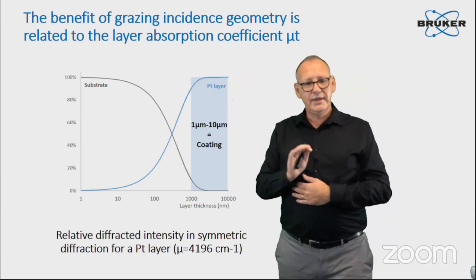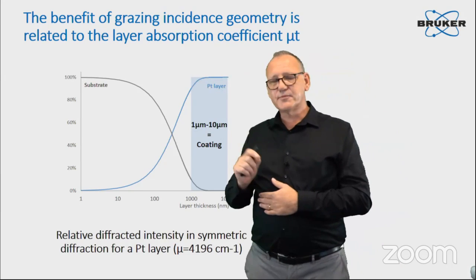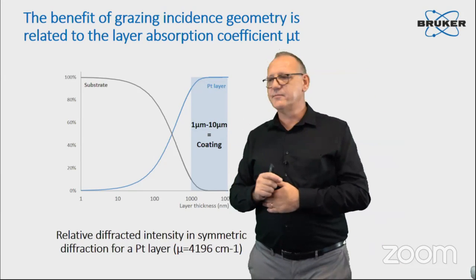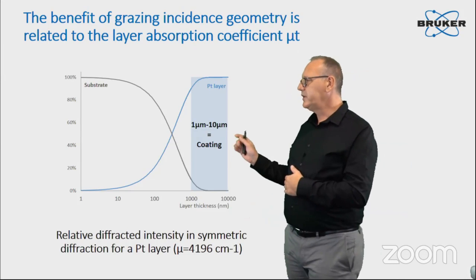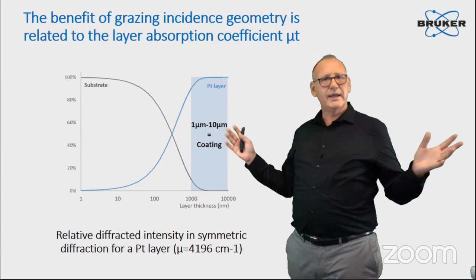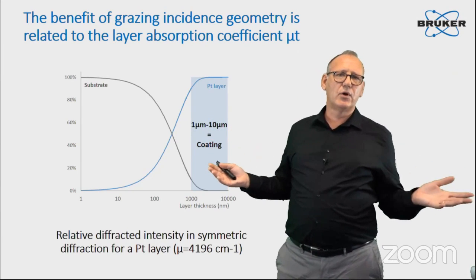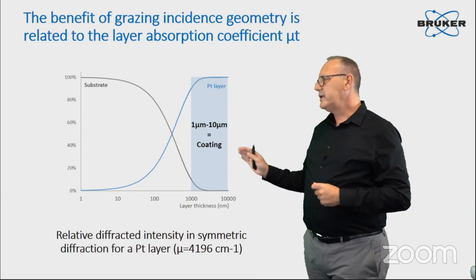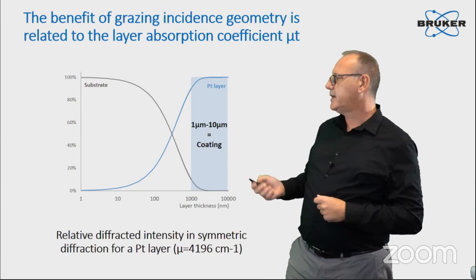So the substrate contribution will be very, very small in your diffraction pattern. So here, for, I would say, thick layers, and I would rather call it a coating, you can keep on using your standard theta-theta diffractometer.